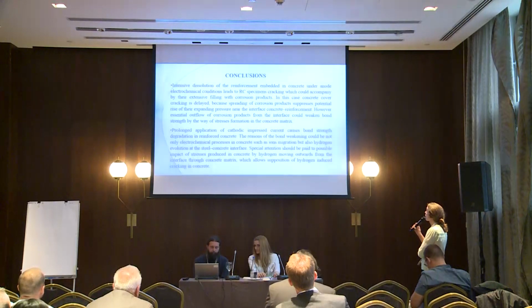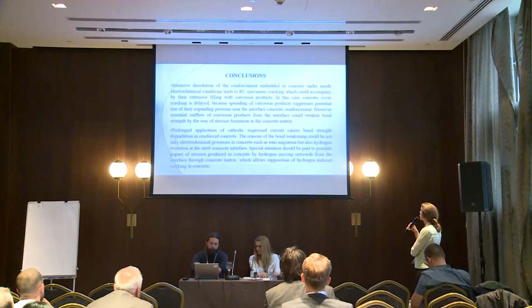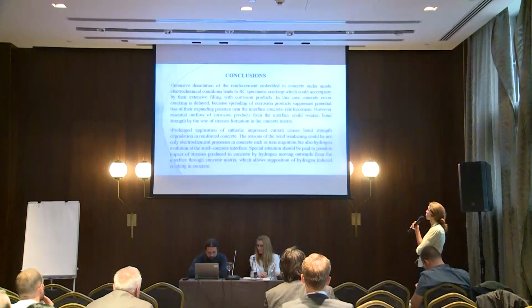Intensive dissolution of the reinforcement embedded in concrete under non-electrochemical conditions leads to cracking of reinforced concrete specimens, which could be accompanied by their extensive filling with corrosion products. In this case, concrete cover cracking is delayed because spreading of corrosion products suppresses potential rise of their expanding pressure near the concrete-reinforcement interface. However, essential outflow of corrosion products from the interface could weaken bond strength by way of stress formation in the concrete matrix. A prolonged application of cathodic impressed current caused bond strength degradation in reinforced concrete.